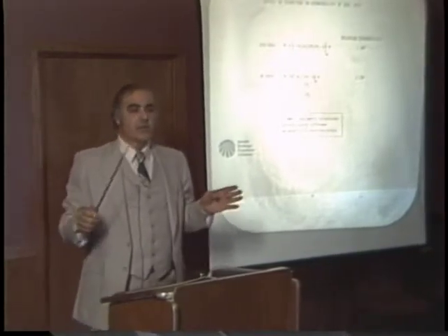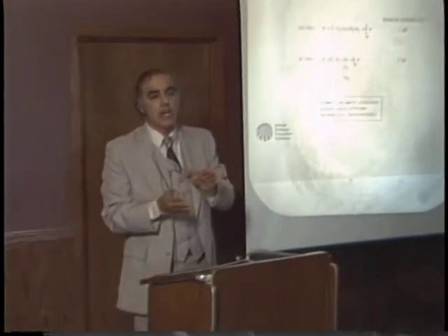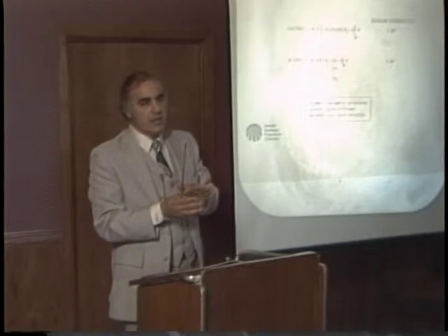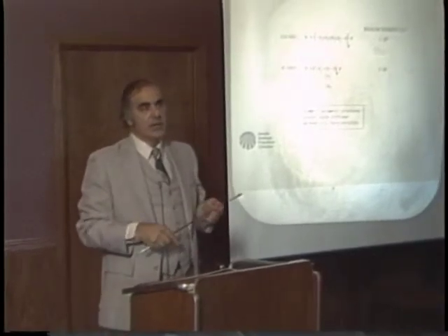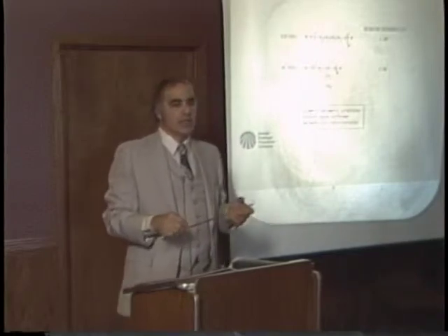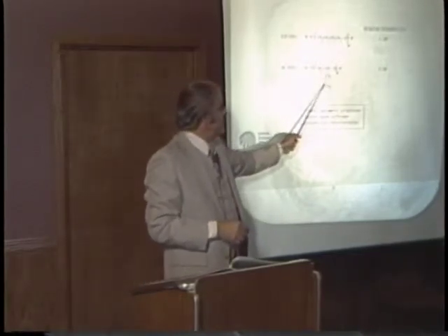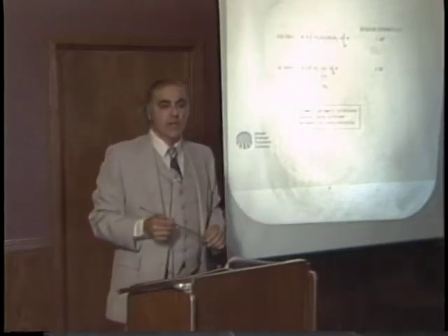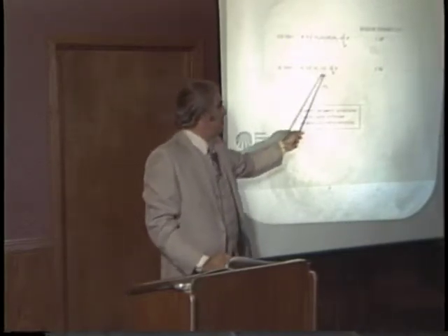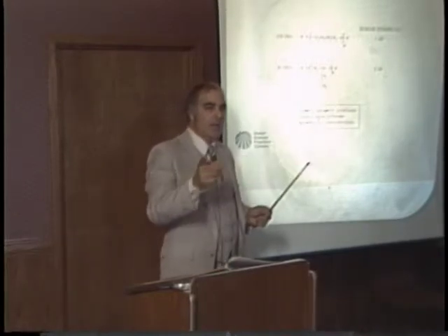Now, what you see with these two is in the 1,4 system, the first one here, there's close association by the chains, and as a consequence, the material in its pre-polymer state is a relatively high melting material. It melts somewhere around 50, 60 degrees centigrade. By contrast, this material is a nice low viscosity liquid at room temperature, because this ethyl side chain prevents close approach of the backbone chain.